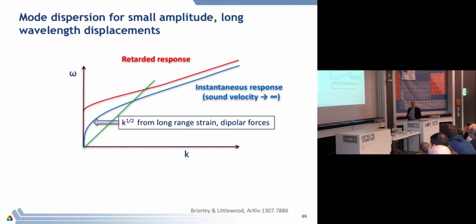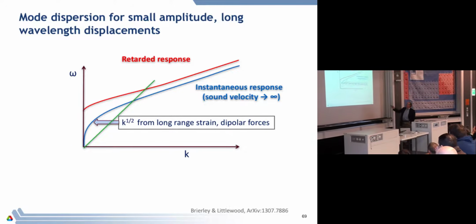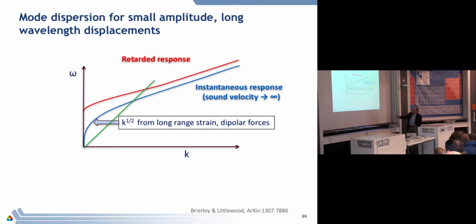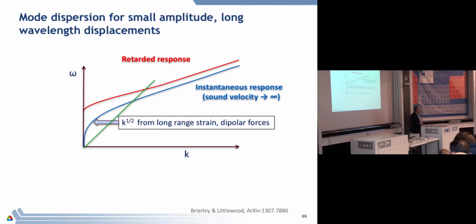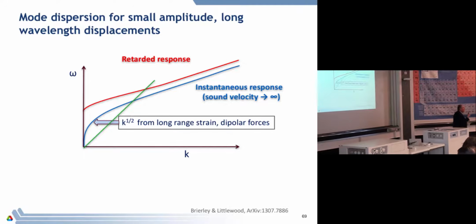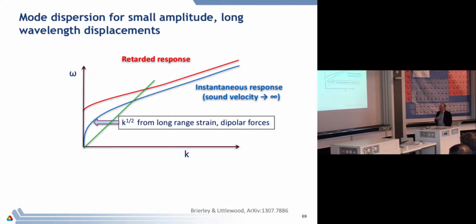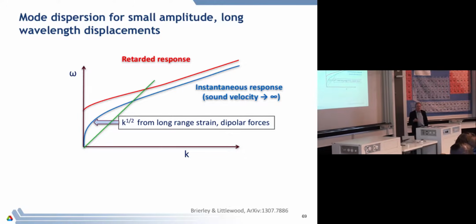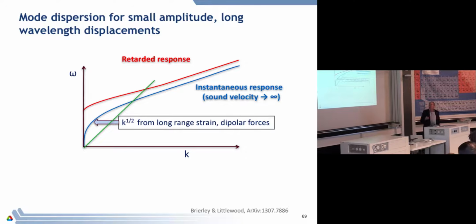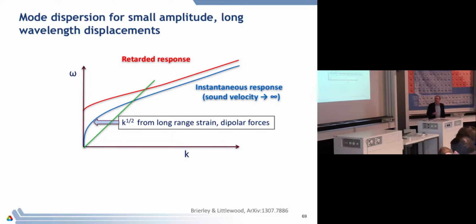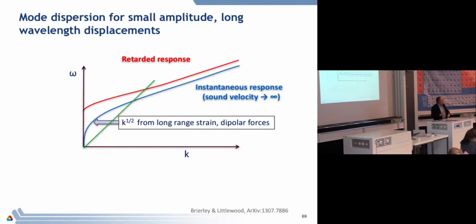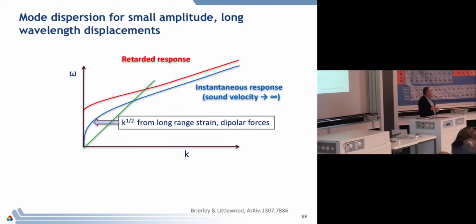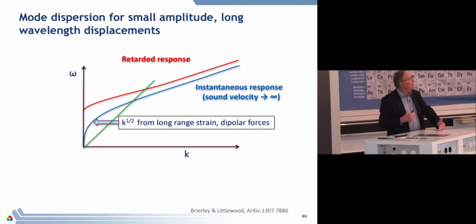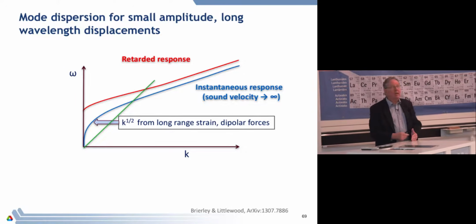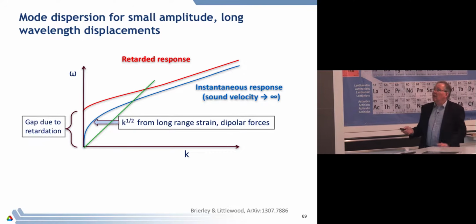Which is somewhat surprising. And it will have a gap, and then it will actually have decay into Cherenkov radiation coming in here. But actually that's something that anybody who works on ferroelectrics knows, because when you switch ferroelectrics, they make a noise. And that's the Cherenkov radiation, which is produced by moving these objects. And the reason this has a gap is that if I try and move this wall fast, the lattice behind it cannot keep up, and therefore it's pulled back. And that can be pretty substantial.